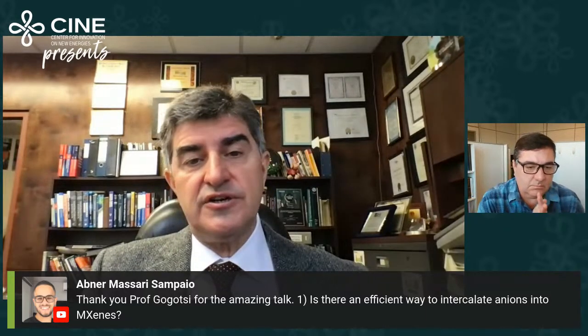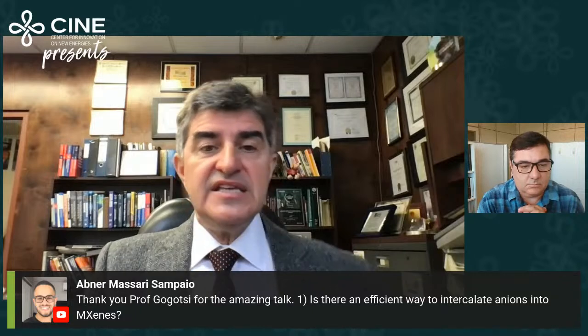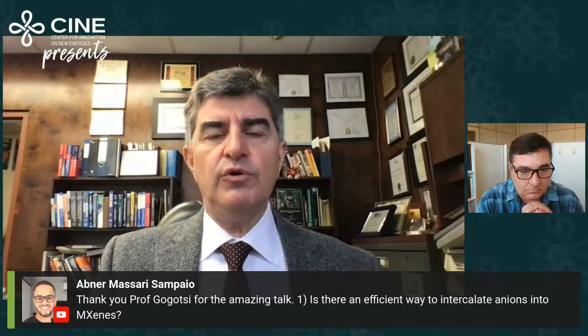Well, that's a very good question. Primarily because of the negative charge of MXenes, cations, protons, easily go even spontaneously between the layers. You can get them in here. For a long time, we believed that anions could not be well intercalated here. We know now it's possible to get anions in, but you need some special conditions. You can get anions in when they're basically pulled by cations, or you need to expand the lattice, with MXene having bridging molecules between the layers that would allow anions to go in. So definitely cations go more easily and readily into MXenes compared to anions, but we know nowadays that anions can also get into MXenes.